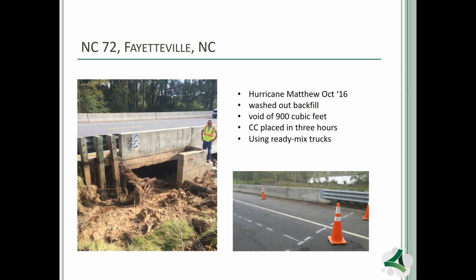Another project, done in Fayetteville, North Carolina, was a bridge abutment that had a small washout, and they replaced the backfill there with 900 cubic feet of cellular concrete that was used with ready mix trucks. The project duration was a total of 3 hours, so it was very short. Because you can literally take a ready mix truck and every cubic yard of a neat cement water mix, you can expand that out to about 3.7 times its volume with the foam.